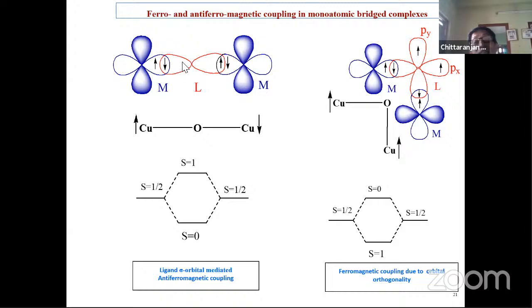When they are like a linear one, copper oxygen copper system, this linear one, that is an antiferromagnetic feature. If it is the perpendicular one, copper oxygen copper, where it is perpendicular to each other, one copper oxygen bond is perpendicular to the other copper oxygen bond, here the spin is ferromagnetic behavior. That means spin orientation is responsible for its magnetic property. In metal organic frameworks, the structural strain may be responsible for this type of spin change.